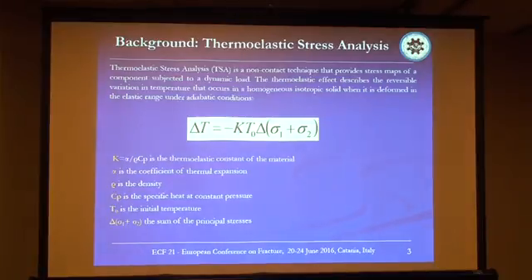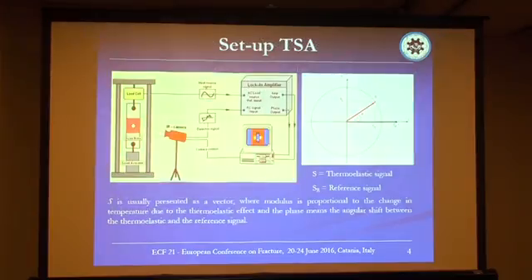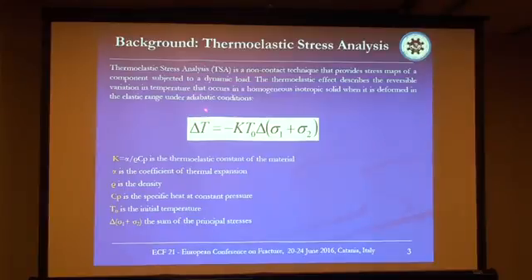Thermo-elastic stress analysis is a non-contact technique that provides stress maps of components subjected to a dynamic load. The thermo-elastic effect describes the variation in temperature that occurs in a homogeneous isotropic solid when it deforms in the elastic range. We can relate the variation in temperature to the sum of the principal stresses through the K-value, which is the thermo-elastic constant of the material.